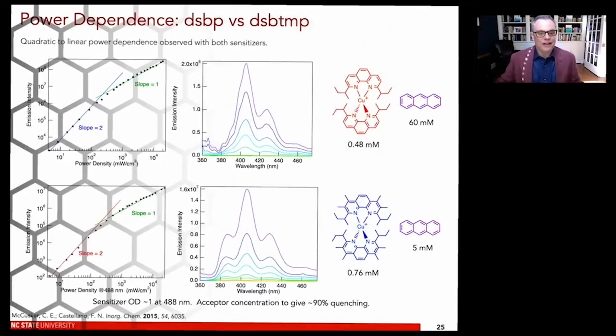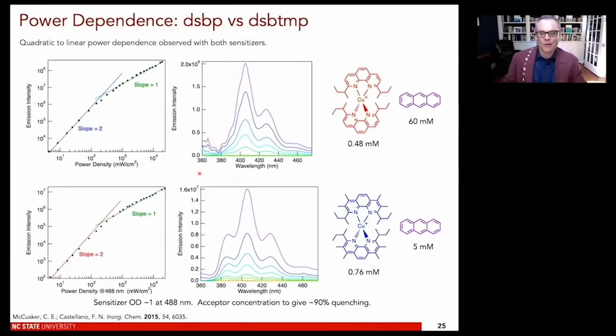And keeping in that idea, what I want to show you too is that you can do all of these typical plots of looking at the upconverted emission intensity versus the power density, or you can actually turn this into absorbed photons. It's all the same. But this is all done with 488 nanometer light. And you basically see that you always get this conversion of quadratic to linear, and where they cross is the I-th value, which I'll get into in a little while.